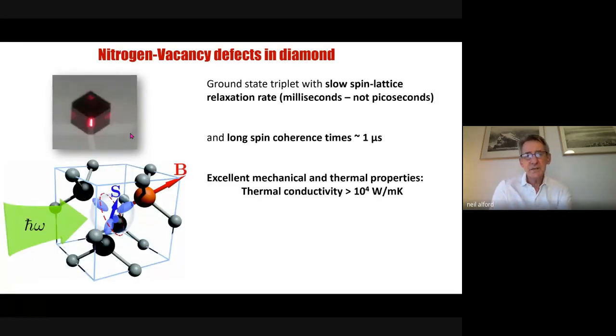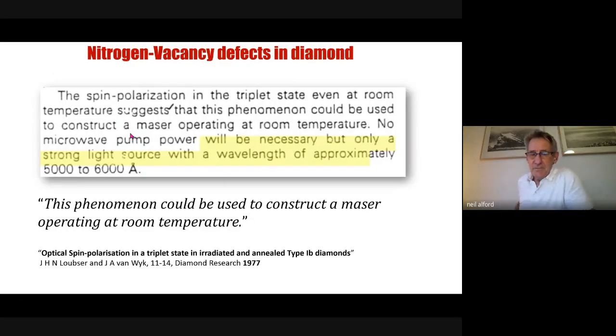And what we found was nitrogen vacancy defects in diamond have quite long spin coherence times of the order of microseconds. They also have a ground state triplet with slow spin lattice relaxation of milliseconds, not picoseconds. And of course, they have fantastic mechanical and thermal properties, with a thermal conductivity of 10 to the 4 watt per meter Kelvin. Now, going back to the literature, we find that nitrogen vacancy defects in diamond had been thought of before, in fact, in 1977. And there was a suggestion that this phenomenon could be used to construct a maser operating at room temperature. Of course, it was never made, but there was a suggestion that it could be.